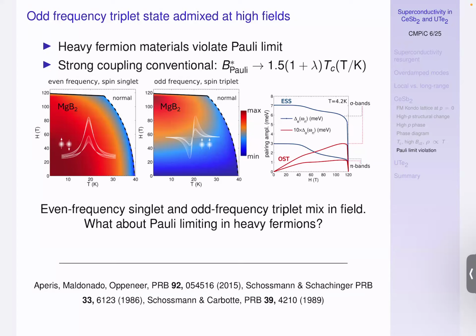If you apply higher field to a conventional strong coupled superconductor, you have increasing admixture of an odd frequency spin triplet state. So in a way, they are actually triplets, you see. Because what happens is that the actual superconducting gap function is a superposition of even frequency singlet and odd frequency triplet. And in high field, the odd frequency triplet is increasingly favored. This isn't my work, of course. This was done 10 years ago by Oppeneer group in maybe Lund, I think, in Sweden.